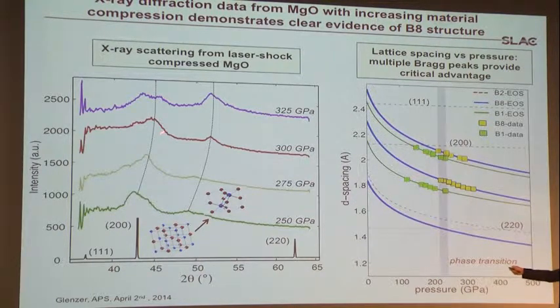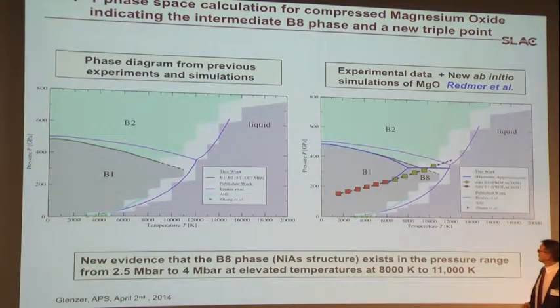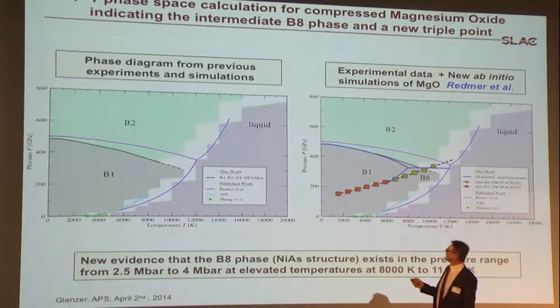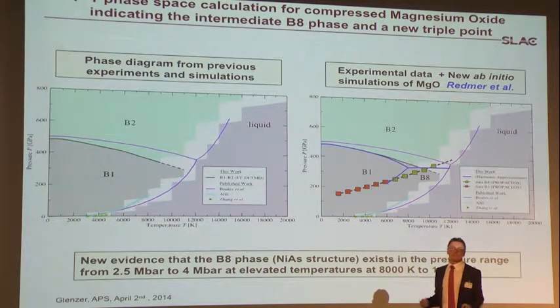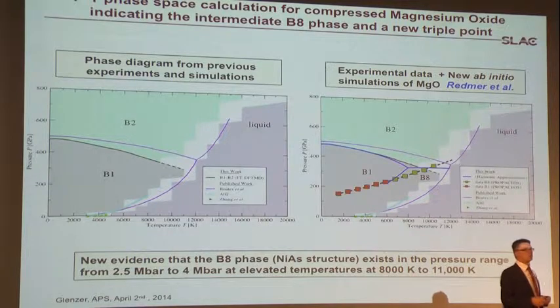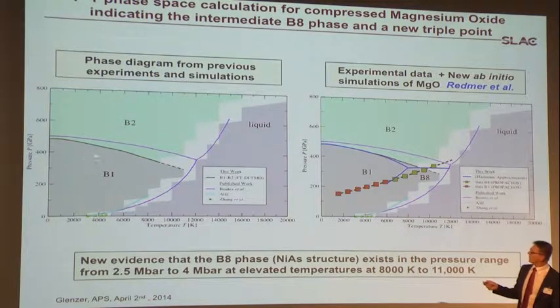And what we find is the splitting here is evidence that you go from a B1 phase to a B8 phase at high pressures and at high temperatures. So now we've asked our collaborators, because this phase diagram was motivated by previous studies on magnesium oxide, on laser-driven experiments, where people have said that there are B1, B2 phase transitions at roughly about 4 megabar or 400 GPa. So if the temperatures are high enough, we may push it into this regime where there could be a B8 phase. So this is still a work in progress, but it's very encouraging.